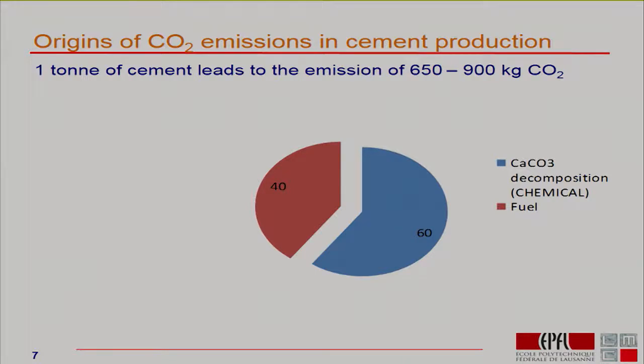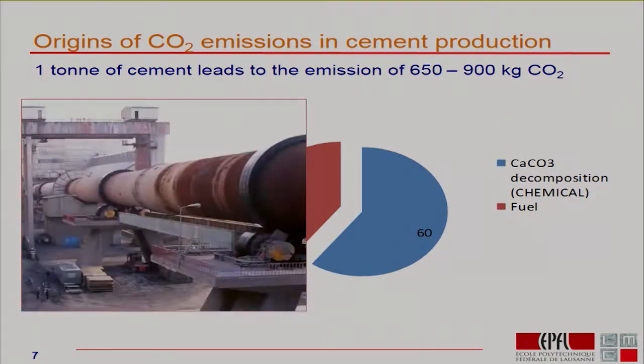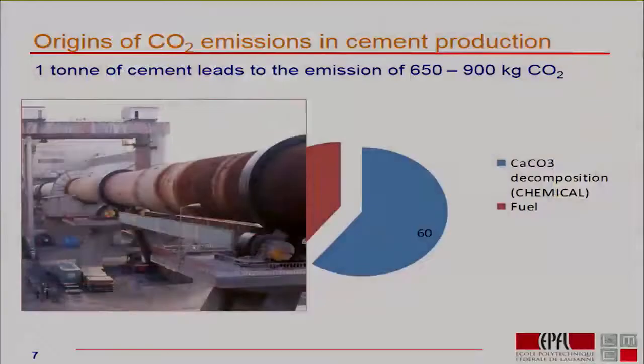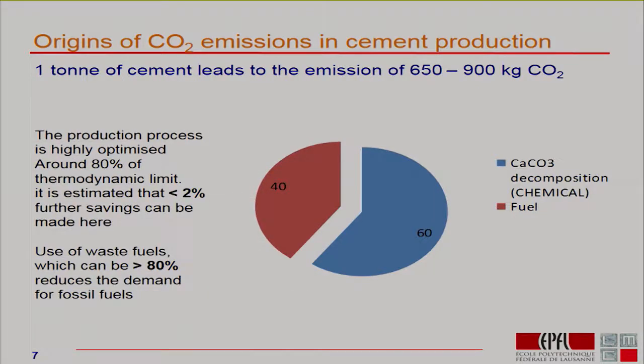So cement accounts for 95% or so of the CO2 emissions in concrete. 40% of the CO2 is coming from the energy used in production. And this is really quite unique in terms of industrial processes, because in most industrial processes, nearly all the CO2 comes from the energy in that process. So if we have alternative energy sources, like solar or wind, then this will largely solve the problem. In making cement, only about 40% is from energy. This is a cement kiln, where you have a huge flame which heats the cement raw materials up to about 1450 degrees Celsius. It seems like a very energy-intensive process, but it's actually very efficient. The efficiency of a modern state-of-the-art cement kiln is around 80% of thermodynamic limits. And those of you who study thermodynamics know you can't really do that much better than that.